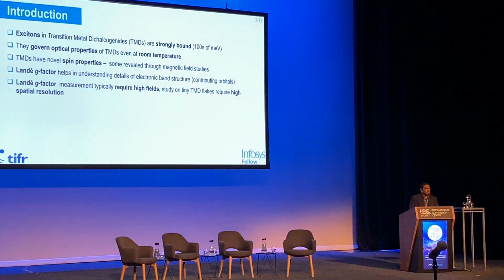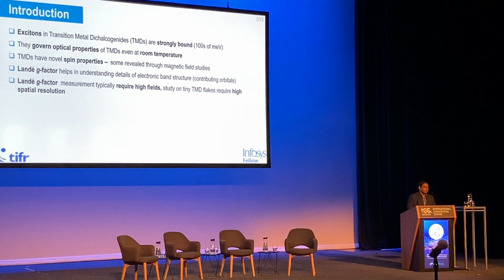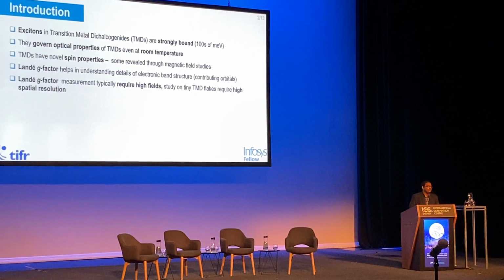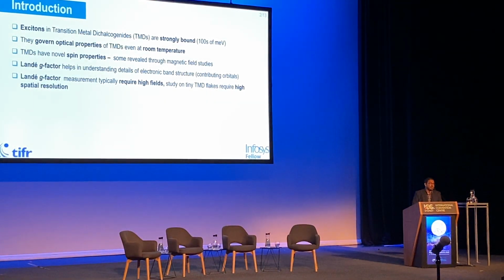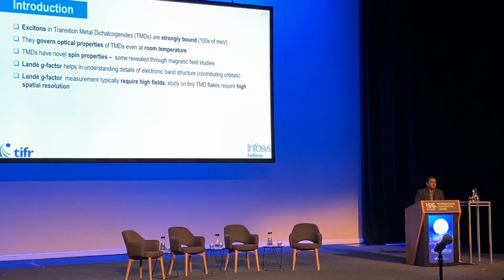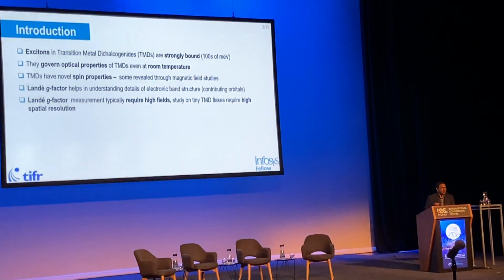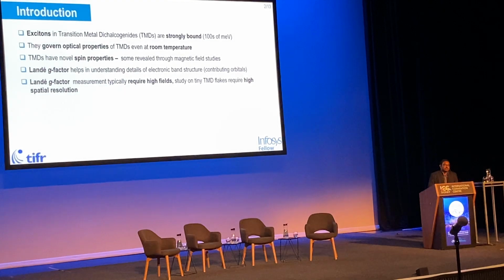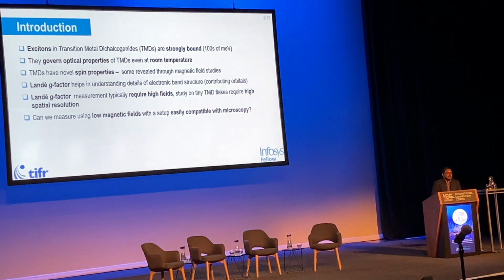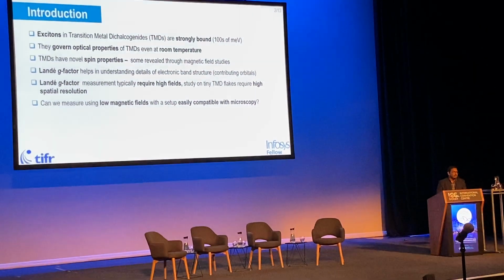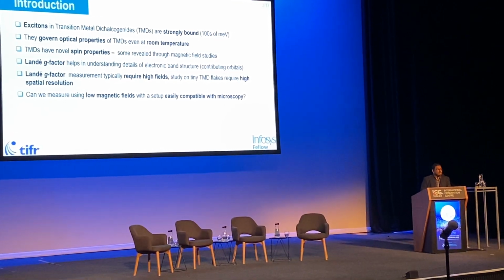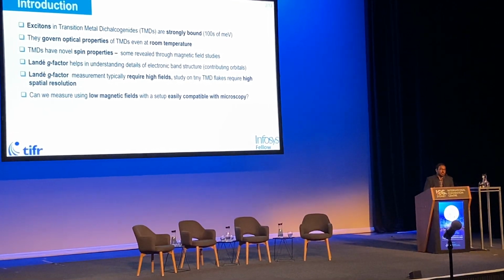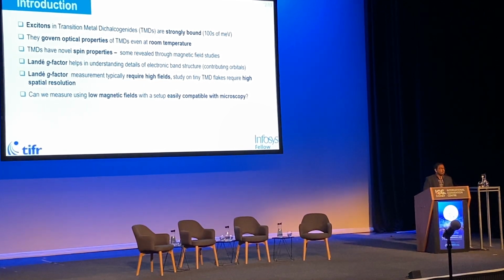But we see that in these TMDs, if we want to extract this exciton Landé factor, it actually requires very high magnetic field, and also the flakes are very small, so we need very high spatial resolution also. So the question we asked: can we measure the same exciton Landé factor using low magnetic field and a setup which can be easily compatible with microscopic arrangements?